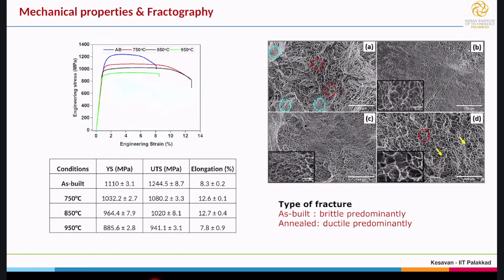Which is good. So 1000 MPa is a good amount of strength. Of course, there is a loss of strength, but at the same time the ductility is restored, which is very good. The ductility is restored because of the formation of beta phase, which is a soft and ductile phase present in the titanium material. This is a nice study we did, and we got a good understanding about processing of titanium material with 3D printing and how the as-printed structure shows, and we could relate that with macrostructure, microstructure and atomic structure level.